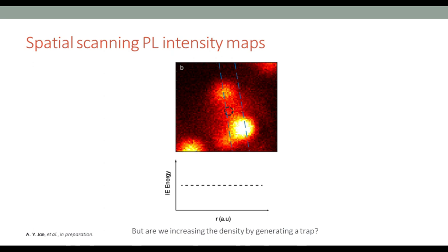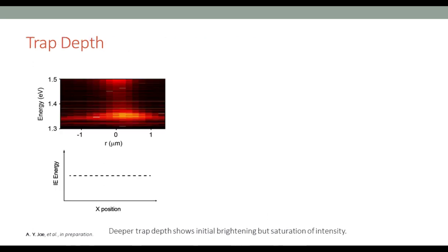However, when you make a trap, what's interesting is that now everything in the trapped region is quite uniform. And now the exciton shape actually resembles the shape of the cloud that we're making. This is promising because whatever naturally occurring traps are happening in our sample, we can actually overcome them with a large enough trap depth. So we look at how much depth we actually need in order to generate a trap, and it turns out to be quite small. This is again a flat line cut, but just by applying a very small voltage, we can see that the trap lights up much brighter, but it doesn't get much brighter as we make the trap deeper.